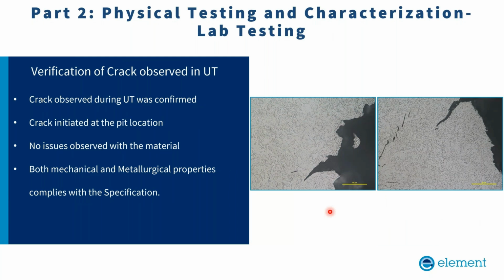Detailed analysis was done, and it was observed that this particular crack actually initiated from a pit location, and due to applied stress, this has propagated through the material. However, there were no issues observed with the material, and as I mentioned before, both mechanical and metallurgical properties comply with the specification of the standard.